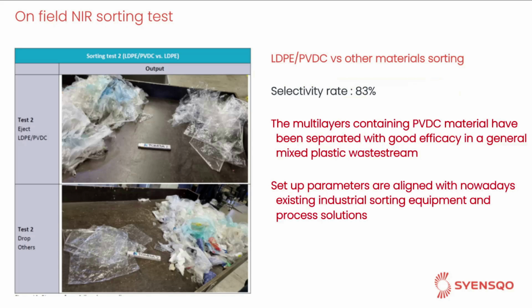What about the result? We used a sort of plastic mix which would simulate a municipal plastic waste stream, and we added a known amount of our multi-layer materials, and we selected to separate this multi-layer from the rest of the plastic waste. And the selectivity rate that we obtained reached the value of 83%. You can see on the right side of the upper part the multi-layer which has been separated from the rest of the plastic mix. And 83% of the multi-layer actually has been separated from the plastic mix.